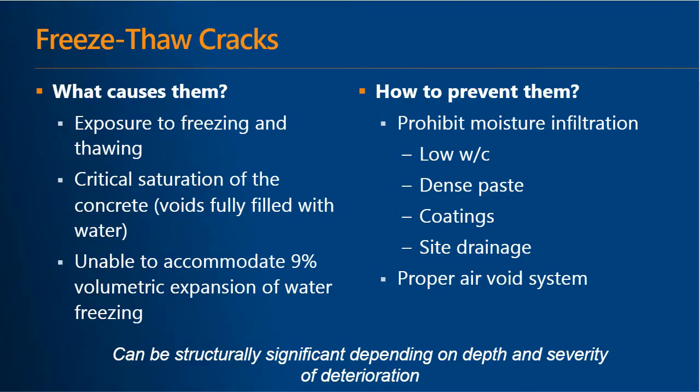But you also need to have a critical saturation of the concrete. And that means that the voids and pores are fully filled with water. And that's because as the water freezes, it has a 9% volumetric expansion. And that expansion, if unable to be accommodated by the concrete, say by empty void space, it will result in cracking. And so you have to have, one, the exposure to freezing and thawing and, two, critical saturation.